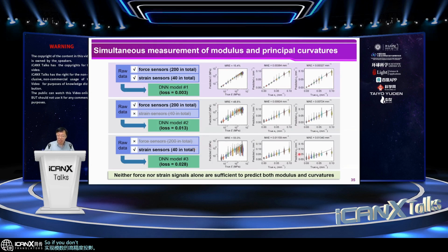Okay, so if you look at the result on the right, you can see a very large enhancement of the prediction for the modulus and also for the curvature components. So in particular, if you look at the mean relative error of the modulus prediction, it's around 15.4% in this fully decoupled device. And this one is much smaller than the partially functional device because this one is nearly 50%. And this is also much smaller than the third case. This one is 55%. So this set of comparison also shows that neither force or strain signals alone are sufficient to predict the elastic modulus.